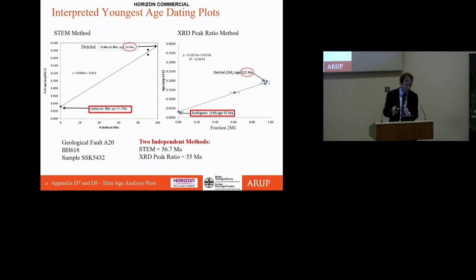And then we plot those up, and what we do is we look at a number of the samples of the clay gouge under the microscope by two different methods, side by side, and we look at what is the proportion of these clay particles that are coming from the wall rock, the detrital ones, what's the proportion that comes from the authigenic ones which are grown in situ, and we want to find the place, the very small particles that are all authigenic, they've grown in place, and we work out the age of those. And you can plot this up on a nice graph, and they happen to work out in a very nice straight line all the time.